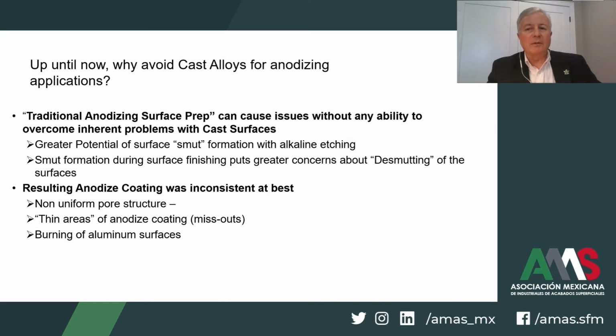So we've had to develop special types of alkaline etching formulations, also acid etching formulations for these. Some examples of defects common for castings included low thickness, what they call miss-outs, with a greater tendency for burning the anodized oxide layer, resulting in inadequate pore structures, which in the end, the pore structure for anodizing is the most critical part to provide high corrosion performance, to get good appearance and decorative performance from these alloys.